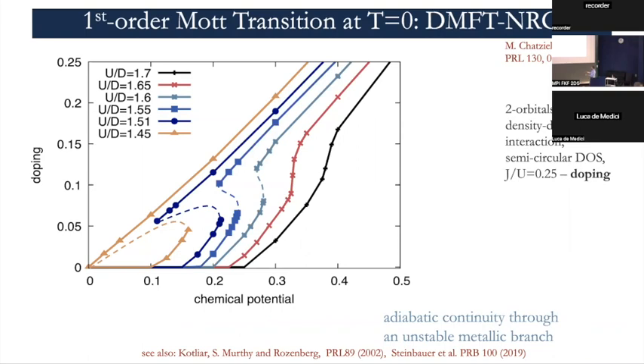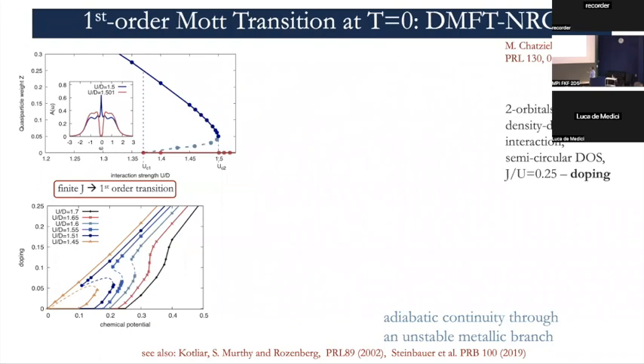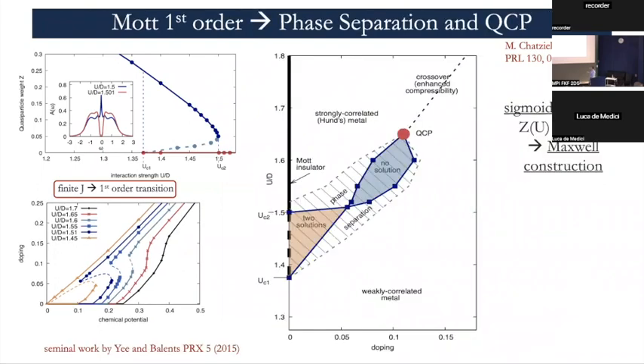So U and chemical potential, and here the fact that this folding is preserved, I mean, we can collect these solutions and trace a phase diagram. So in the phase diagram you have this metallic part which corresponds to this part at low U, large doping. You have a metallic part emanating directly from the Mott insulator, which is this line here at zero doping, at half filling. So it's this zone, which is another metal, and if you calculate the quasi-particle weight, you will find it is much smaller than this one.